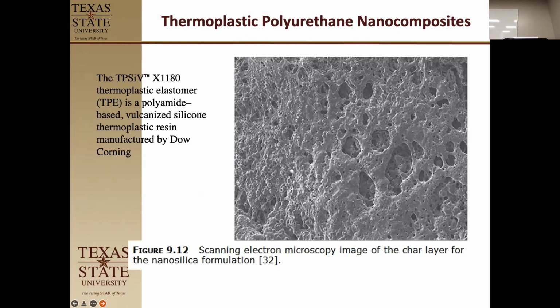And this is the image of the char layer for the nanosilica particles. So they took this thing and added nanosilica particles. The thing you notice here is that, number one, we have porosity. You want porosity in your char layer. This is going straight down, so you can't actually see the bubbles underneath, but these are larger bubbles underneath where the little holes are. And so we see a nice consistent layer across the surface. We see nice porosity. We see it was outgassing properly during its ablation.